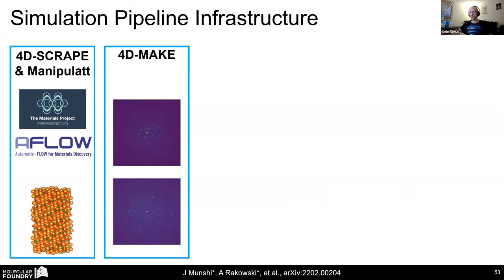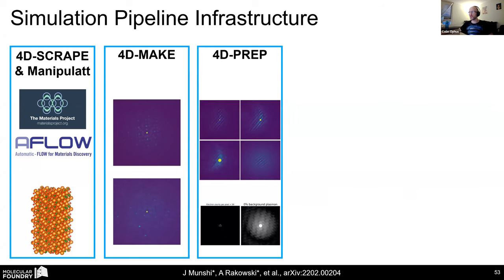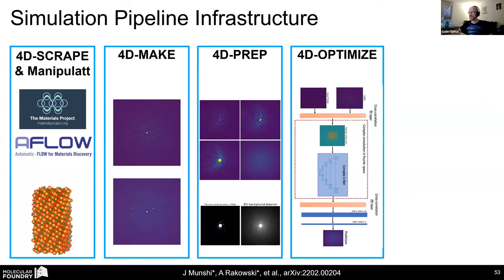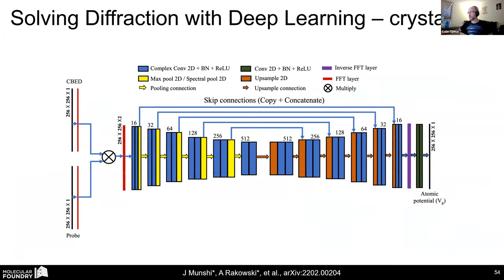We simulate hundreds of thousands of these diffraction patterns. We apply elliptic distortion, limited signal to noise, inelastic plasmon backgrounds. And then we train neural networks to invert from these really, really complicated diffraction patterns back to the underlying structure factors. And so I'll just show you one of our architectures here, the FCU net, the Fourier space complex unit.